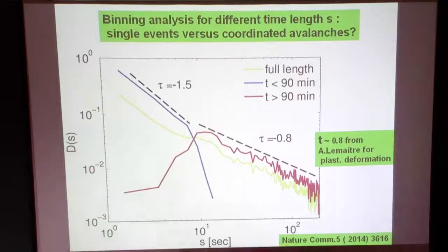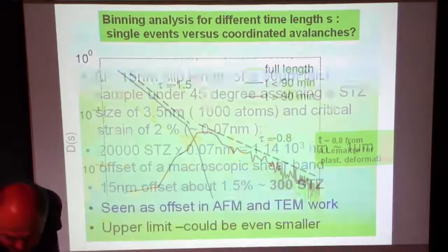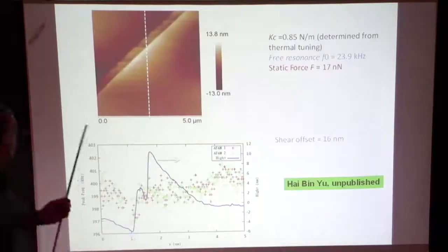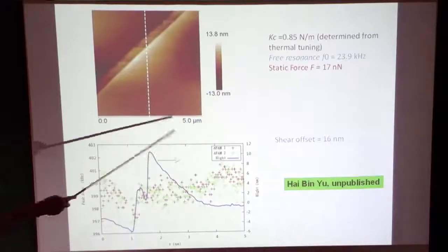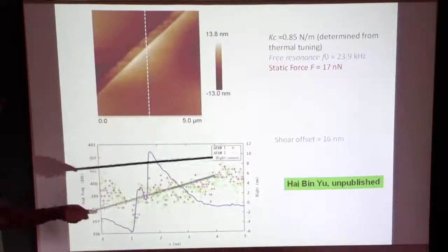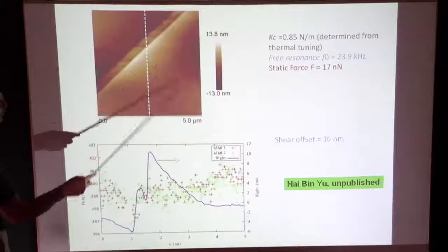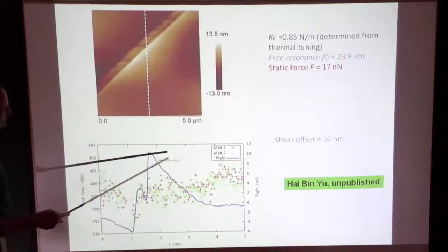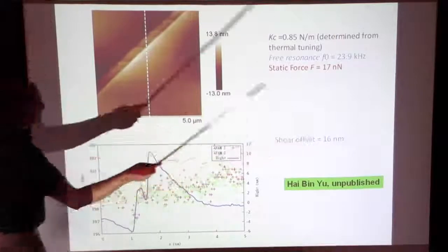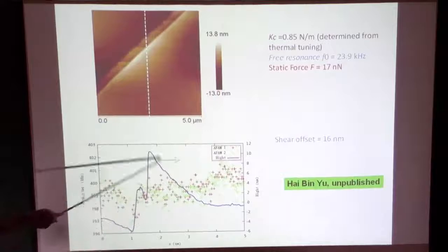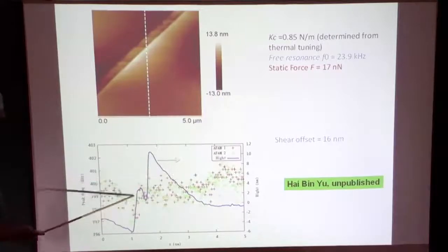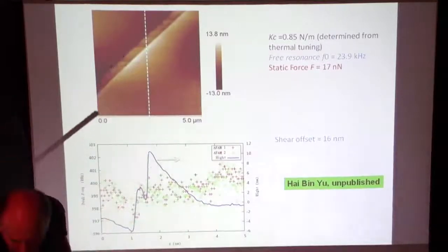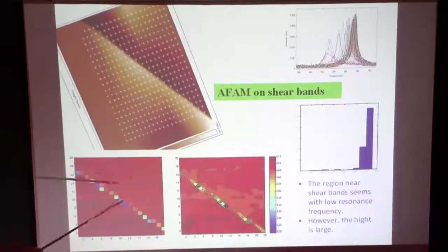And to make sure that this is not, we can see the offsets. We can see the shear bands with the AFM again, atomic force microscope. We can see actually the cutoffs, the shear offset of 16 nanometers. We find those actually. We find the modulus changes here. I can show you locally how the modulus along the shear band looks like.